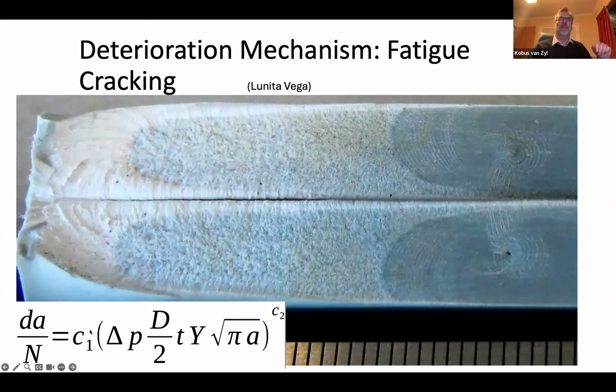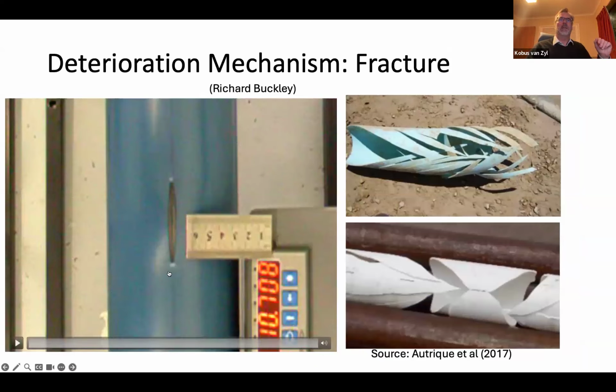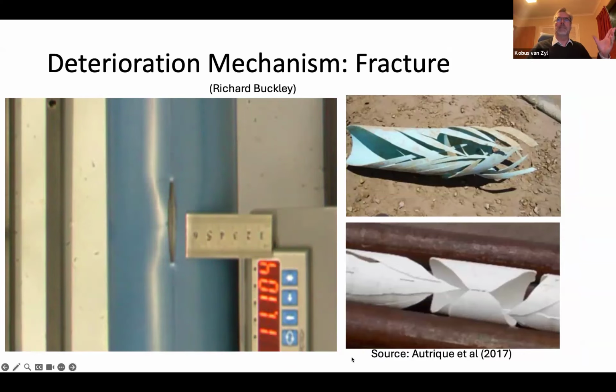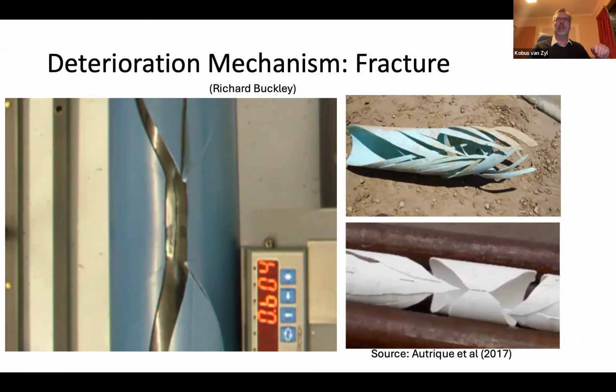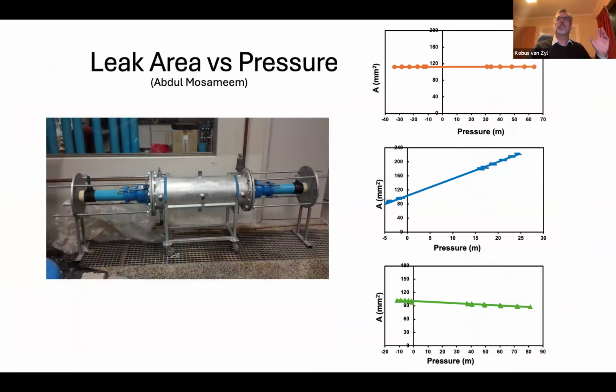And this is interesting because the length of the crack, which is a, is not a function of pressure, but it is a function of the change in pressure. So the pressure variations and the number of cycles drive this process. And then finally, at some point, based on the length of the crack and the pressure, you get a complete catastrophic failure that you see there. We used a hydraulic balloon to pressurize it, just to illustrate that process. So those are the mechanisms.